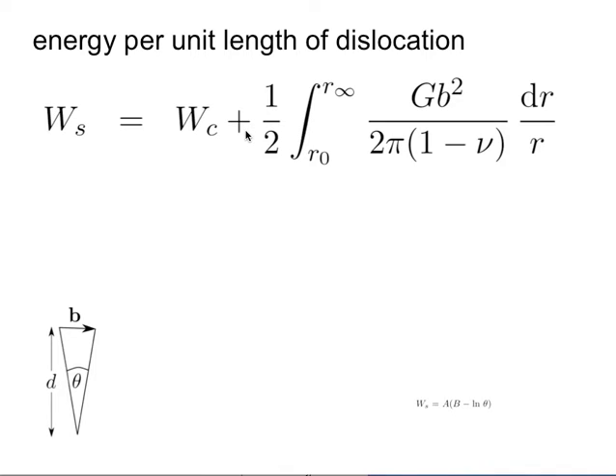Okay, and that's the core energy, and G is the shear modulus, and b is the magnitude of the Burgers vector, and nu is the Poisson's ratio. So you're probably familiar with the equation that the energy is proportional to Gb squared, right? Yeah. So this is the more sophisticated version of that. You've got the shear modulus, the magnitude of the Burgers vector, and in addition you need information about the Poisson's ratio. And the elastic strain field extends from the diameter of the core of the dislocation to infinity in this equation. But real crystals are not infinite in size. So if we just have a crystal, it will be the size of the crystal which gives you the upper limit of this integral.